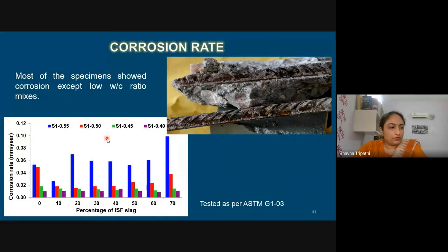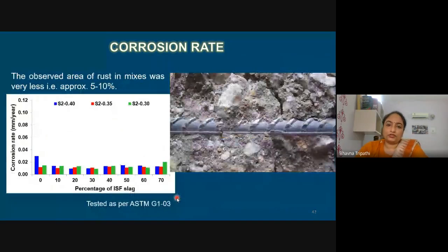And how do we compute the corrosion rate? Earlier, both observations were based on measurement of current or potential. This was the final test, when we broke the samples and visually observed the condition of the reinforcement. We found that there is corrosion, and the corrosion rate was computed. It was seen that most of the samples with higher water cement ratio had developed corrosion. However, for the samples having lower water cement ratio, there was nil or very little corrosion.